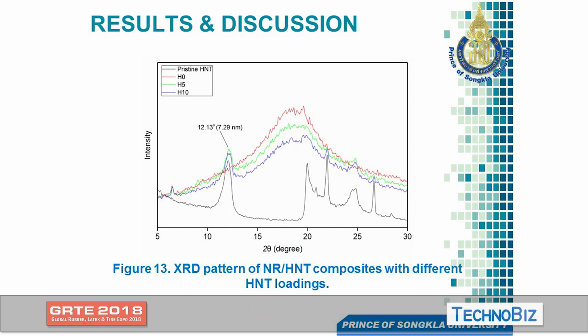This is the typical XRD, the common XRD, without wide-angle or small-angle X-ray. Here we can see the peak of interest of the HNT, which is at 12.13 degrees. This is the crystal peak of HNT, just to confirm whether the HNT is there or not. Once we include the HNT inside the rubber, this is the pattern of natural rubber filled with HNT. We can see a hump here, which is the amorphous region, so the curve is not linear as in the case of HNT.